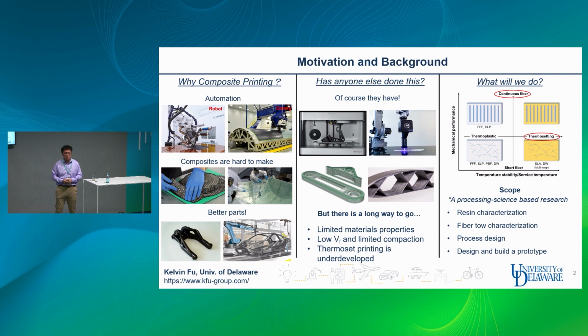So thermoset, or what we call epoxy, 3D printing for composites has actually not been developed yet, because a lot of people are still using UV resin to do the printing. But UV resin has poor mechanical strength and limited mechanical properties, and the cross-linking density is pretty low. If you shine light on the UV resin, the UV light cannot penetrate through very thick carbon fiber or other fiber materials. That causes a limitation. And if we look at this diagram, the only way to achieve high-performance composites is to use continuous reinforced carbon fiber plus thermoset. Okay, so here is our work.